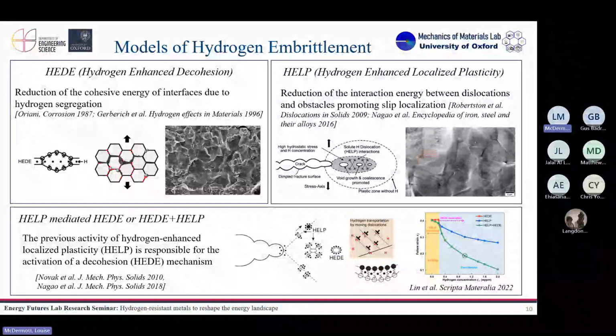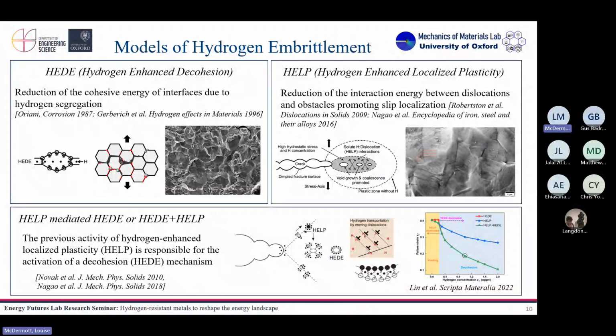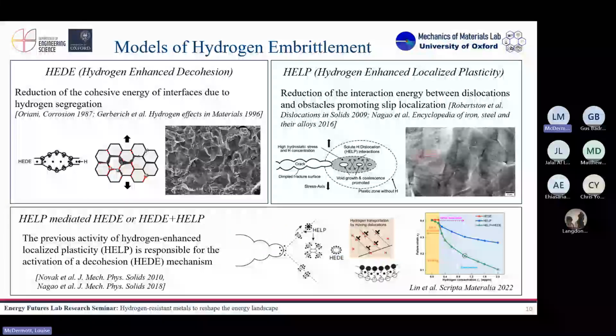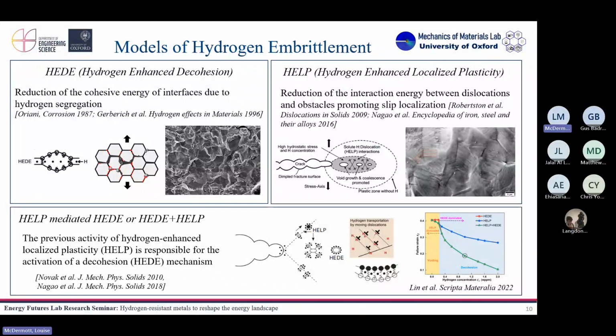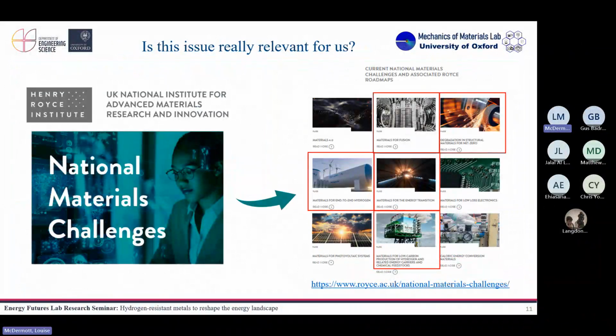And that's going to provoke this more premature final failure. Then some other researchers say that these two mechanisms need to happen at the same time, or that one needs to mediate the other, so there needs to be synergy between both for them to really provoke this damage in your material. So basically, they say that dislocations may be helping hydrogen move to those defects, where then you have some kind of decohesion. So we have two mechanisms that can work together in very complex ways. Dislocations and plasticity are playing their role, and we are studying those phenomena. And actually, I'm not making all this up. I want to show you that this is a real issue for us.